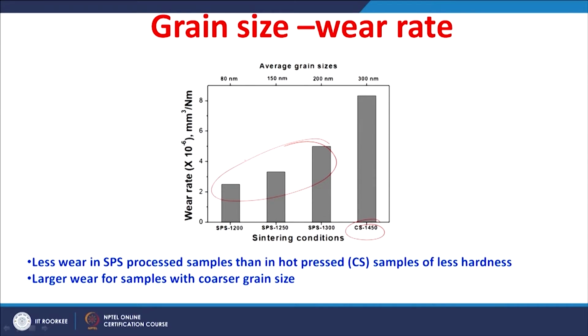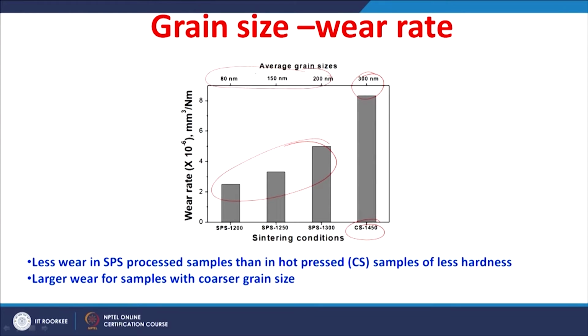In addition to that, with respect to the grain size, the conventionally sintered material has an average grain size of around 300 nanometers, whereas spark plasma sintered ceramics have a much smaller grain size of around 80 nanometers minimum. With changing sintering temperature from 1200 Celsius to 1300 Celsius, the average grain size changed from 80 nanometers to 200 nanometers. The wear rate was less for the spark plasma sintered ceramics having finer grains, whereas the coarser grain material showed a larger wear.